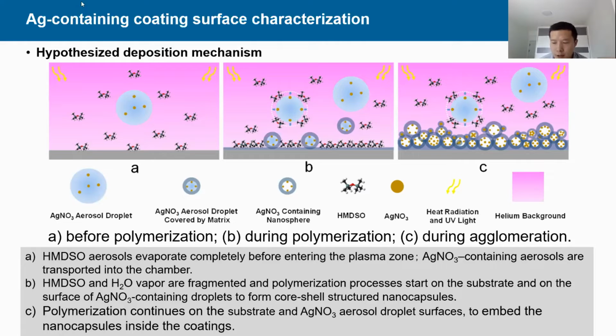In the second stage, HMDSO and the water vapor are efficiently fragmented, and the polymerization process starts on the substrate as well as on the surface of several nitrate-containing droplets. Meanwhile, several nitrate aerosol droplets are continuously evaporated and transported to the substrate due to the sedimentation and diffusion. This results in the formation of nanocapsules covered by the polymeric matrix. In the third stage, the polymerization continues on the substrate and the droplet surface to embed the nanocapsules inside the coating. As the polymerization proceeds, neighboring nanocapsules grow in size and start to connect and intersect, as also seen in some images.